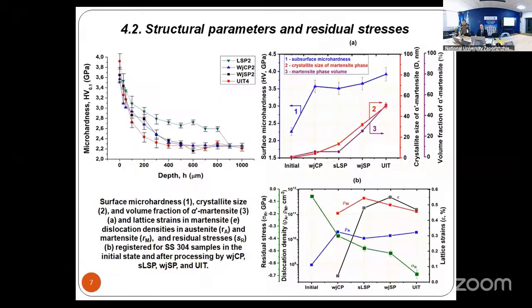Considering the near surface micro-hardness, it's observed that the Vickers values were increased after all peening methods used due to the near surface nanostructuring, as well as increase in dislocation density and martensite transformation in the surface layer. The hardening depth was respectively achieved about 150 micrometers, 225 micrometers, 400 micrometers, and 800 micrometers after the ultrasonic, wet shot, cavitation and laser peening techniques used.